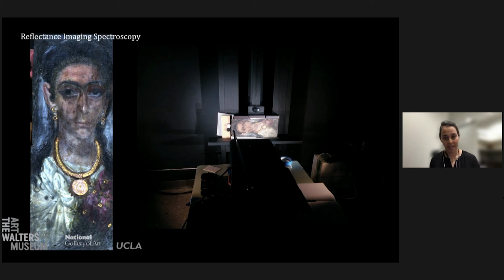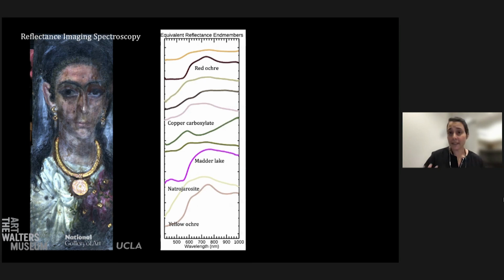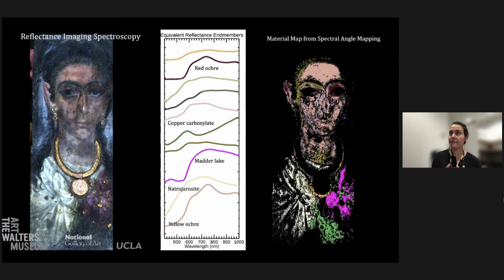We took the hyperspectral camera from the National Gallery of Art to the laboratories at the Walters Art Museum and did luminescence imaging spectroscopy, as well as reflectance. The reflectance data, when we mined the data cube, showed us a bunch of different end members or spectral profiles that comprise the painting. And when we make a map, we see that there are a lot of interesting mixtures, but it seems to be mostly made up of red ochre, yellow ochre, natrojarosite. We know from elemental analysis there was lead white, so all of these are mixed together to create the flesh tones. And the green seems to be made of a copper carboxylate, so it's dominant in copper.